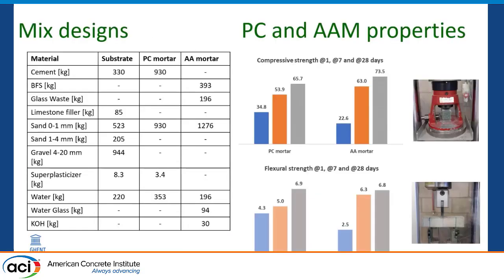Here you can see mix designs for the concrete substrate for a near surface mounted application, then the PC mortar that we use for comparison reasons, and alkali-activated mortar that we use for main research. So here you can see that compressive strength development between PC mortar and alkali-activated mortar follow similar trends. The same can be said for flexural strength.